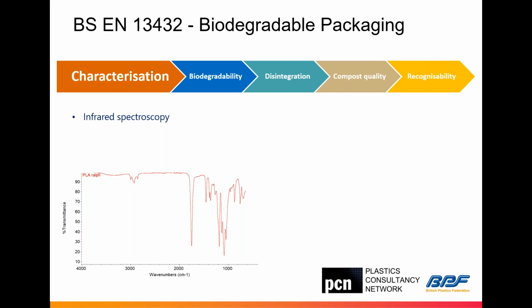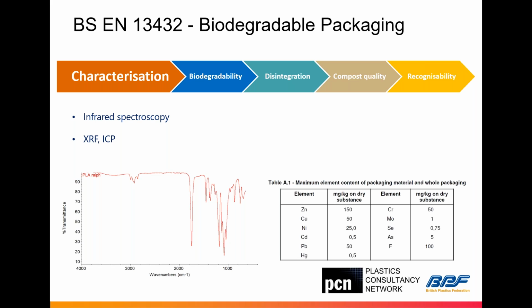The first thing we do is infrared spectroscopy. We need to identify all the main components of this packaging material. We need to know all the additives, even down to 0.1%, before we do any test. The second step is a heavy metal analysis, not so much with XRF, but with ICP, because the limits specified in the BS EN 13432 are so low. So we need to be accurate enough. That's why we're using the ICP method, inductively coupled plasma, coupled with optical emission spectroscopy. As you can see, for example, for cadmium, the limit is 0.5 milligrams per kilogram. Molybdenum is 1 part per million. So it's very strict there about the heavy metals.